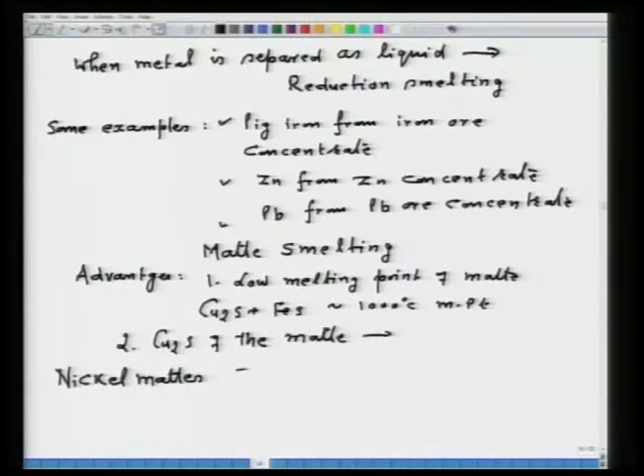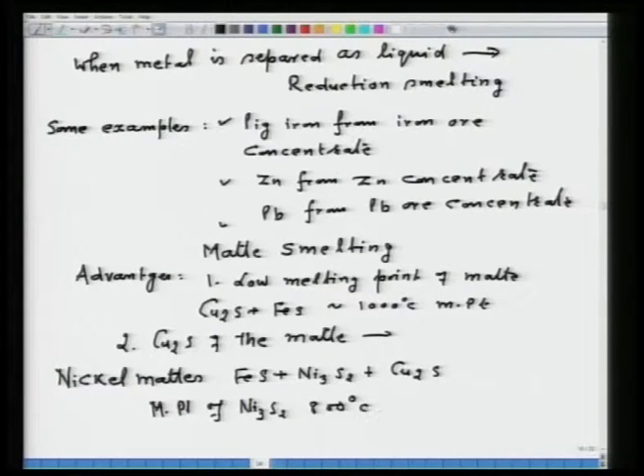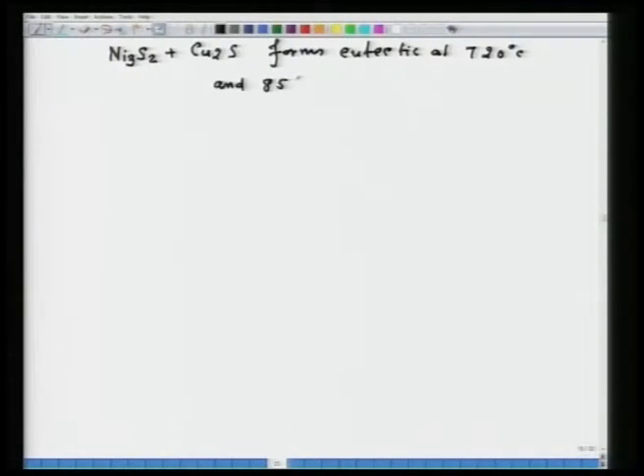nickel mattes typically contain FeS plus Ni3S2 plus Cu2S. Now, here the melting point of Ni3S2 is around 800 degrees Celsius, whereas Ni3S2 plus Cu2S forms a eutectic, if you see the phase diagram, at 720 degrees Celsius and 85% Ni3S2.